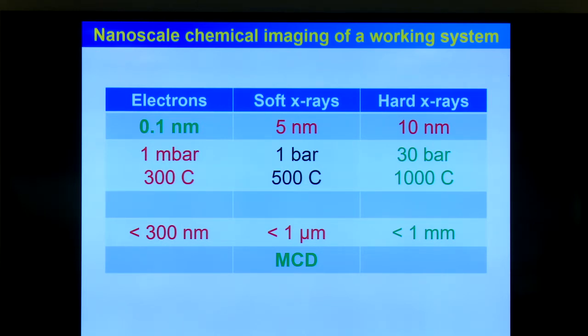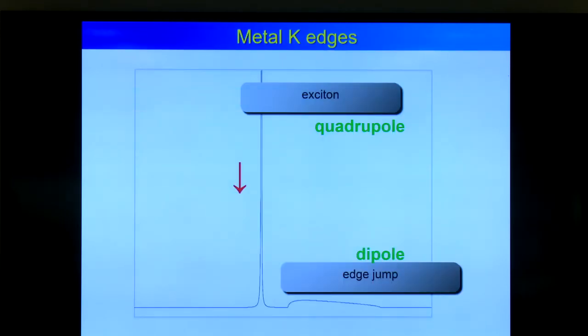Okay, so if you work with hard X-rays, till now we have only seen soft X-rays, so now I switch to hard X-rays. A quick thing on metal K edges. You interpret the spectrum again with excitons and edges. Now the interesting thing is that in transition metals the exciton is quadrupole and the edge is dipole. And the quadrupole is 1,000 times weaker, so this peak goes down by a factor of 1,000, so it's much smaller, and that's the pre-edge in your metal K edge.